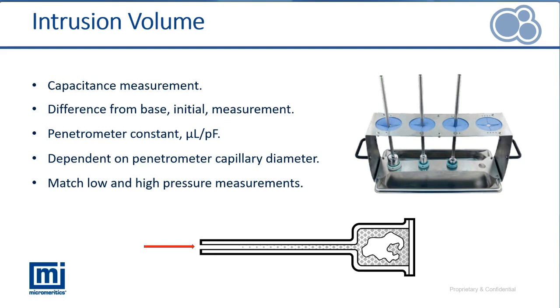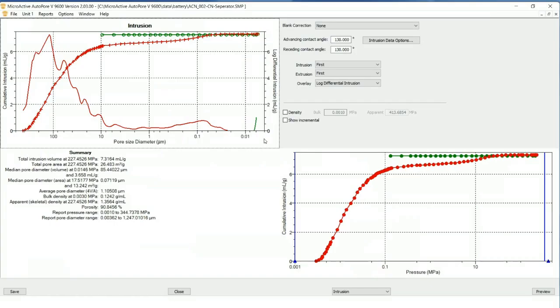Speaking of the software now, let's pause a little bit from this presentation, and I want to take you over and just highlight some of the features in the software. I have an example of an analysis of a separator sample that we can look at. So here we see an analysis of a separator. This was an analysis where we started at a low pressure, less than 1 atmosphere, a subambient pressure, and with filling of the porosity as we go along.